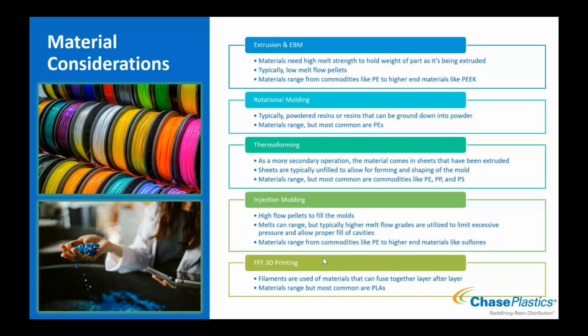Rotational molding, as we mentioned, uses a powdered resin. So you're either going to use a material that's already in powdered form, or a resin that can then be ground down into powder. The most common material for this is polyethylene. They use that one most commonly. You can use other materials, and they have been used successfully. Polyethylene and the commodities tend to be the more common ones for this process. Again, it's got to be in powder form or ground down into a powder form.